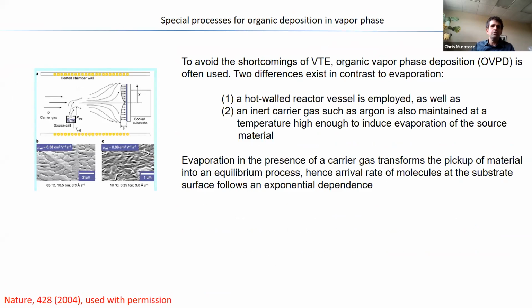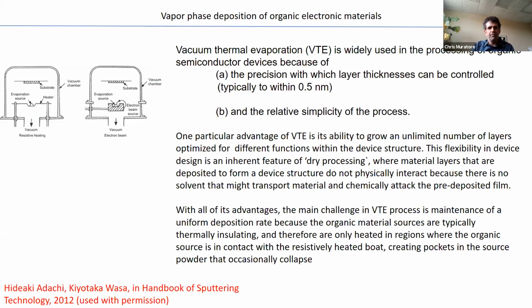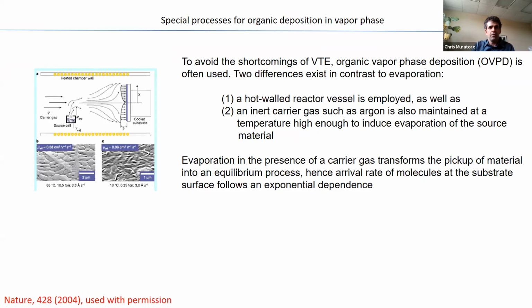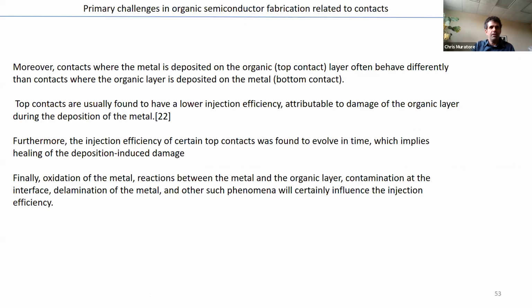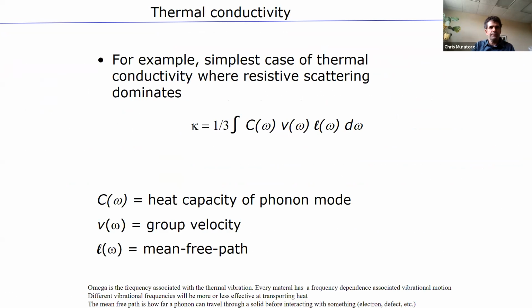You can do organic vapor phase deposition, where you blow the precursors into the chamber and you take care of making them homogeneous before they're introduced into the system to aggregate or coalesce on the substrate. So vacuum thermal evaporation is useful for investigative studies. If you want to make large areas or make production polymers, then you probably want to use some kind of organic vapor phase technique. I'm going to skip this.